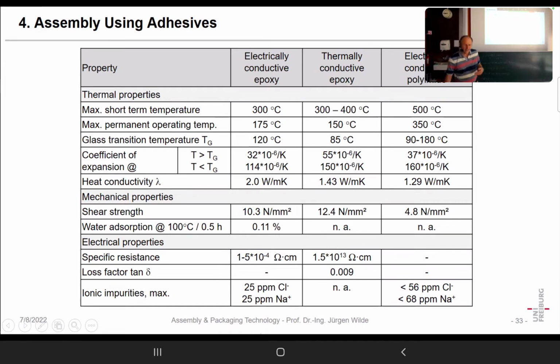For the conductive adhesives, you can have very different glass transition temperatures. In most cases, the glass transition temperature is maybe around 100 degrees centigrade, plus minus, let's say, 30 or so. There are also epoxies you need, for instance, for sensors, that have a higher glass transition temperature. A typical CTE value is 30 to 50 ppm per Kelvin, or 10 to the power of -6 per Kelvin, below the glass transition temperature, and roughly 3 to 4 times higher above it.